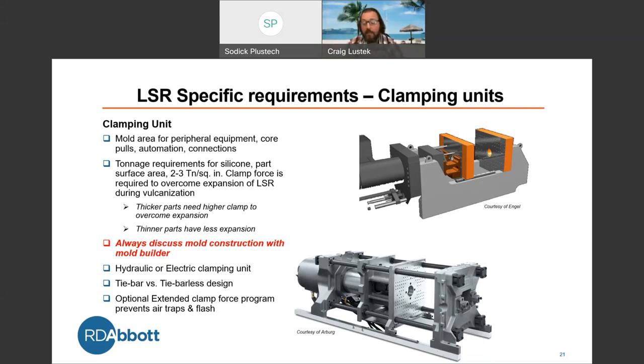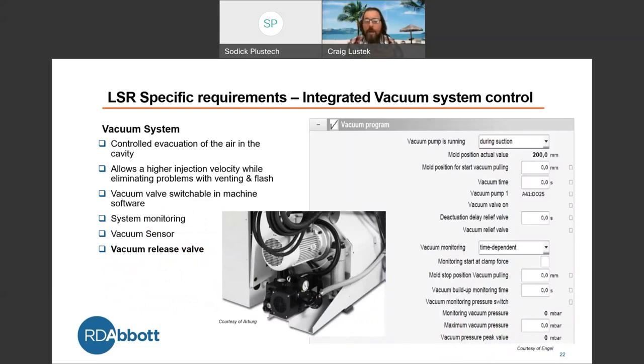Options of extended clamp force program to prevent air traps and flash. Options for liquid silicone rubber molding. You have a vacuum. So a vacuum system is set up to evacuate the air in the cavity, not the whole mold. We just want to focus on that cavity. So this allows us a higher injection velocity, while eliminating those problems where we might run into venting or flash issues.